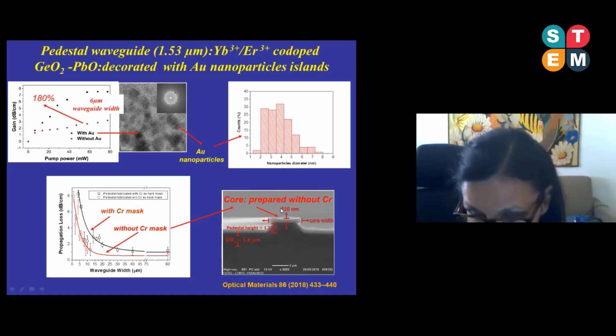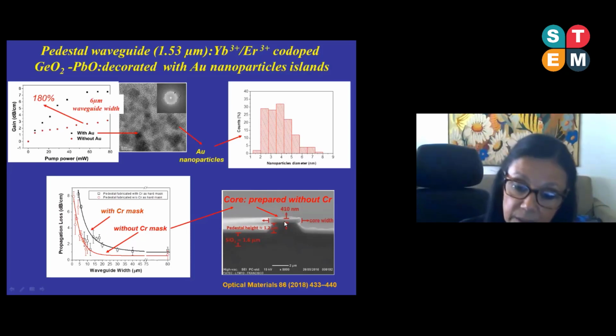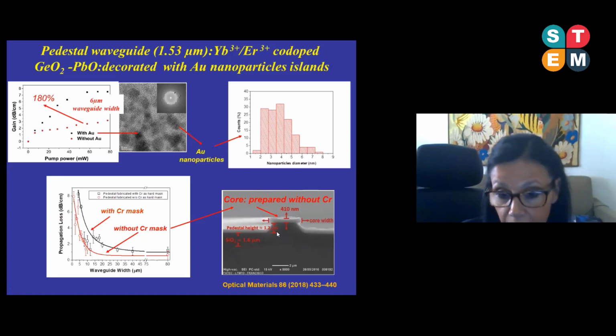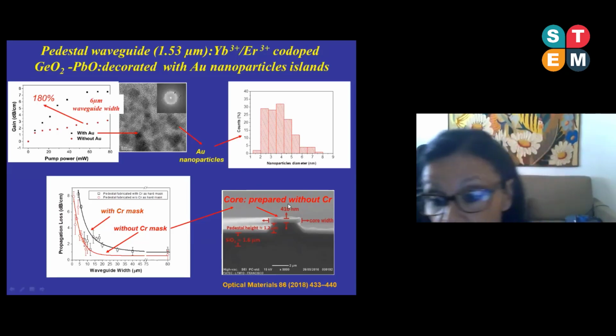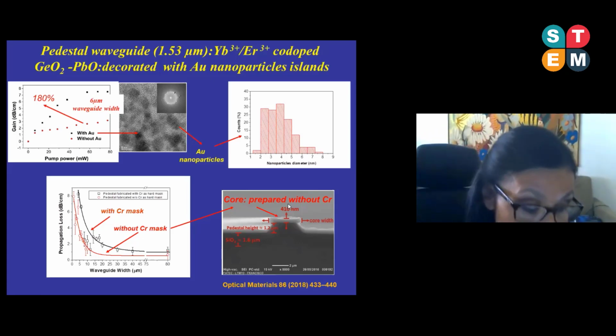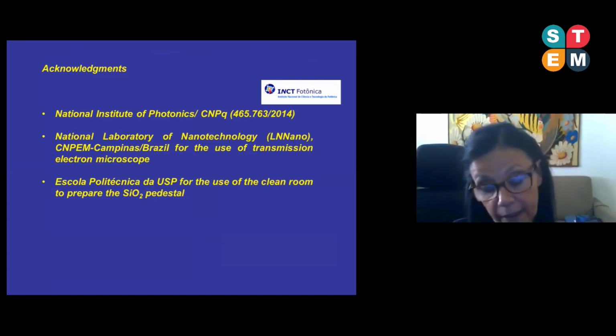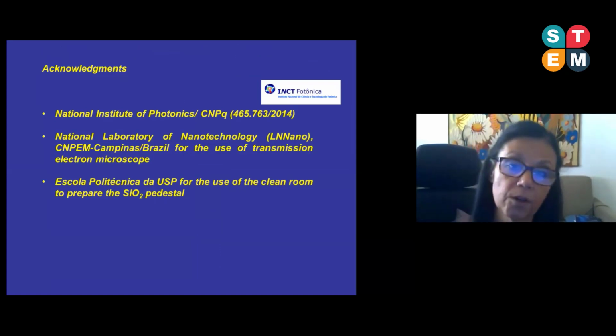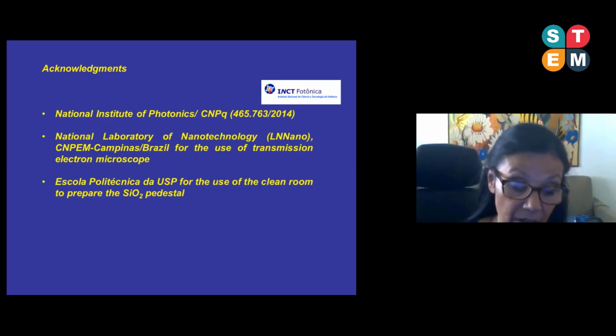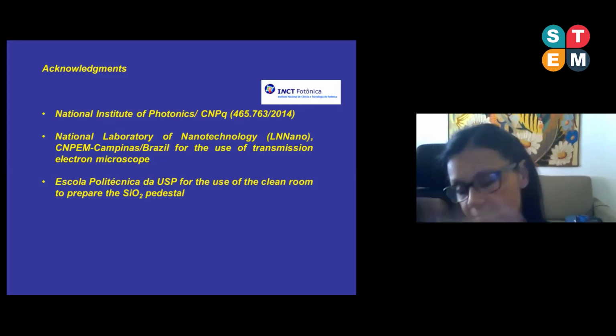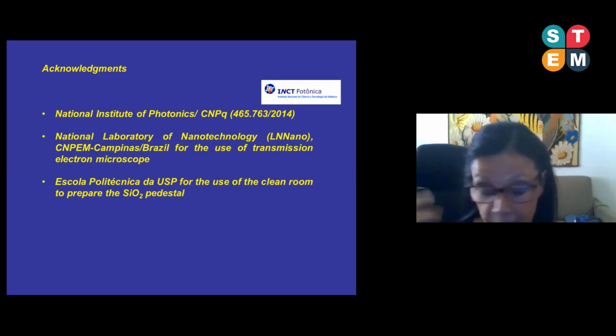In this figure, I show you, also obtained by scanning electron microscope, the profile of the waveguide with a height of about 400 nanometers. And in this case, the silicon dioxide pedestal has a height of 1.2 micrometers. I also would like to add that in this case, the core was prepared without chromium mask. Well, as conclusion for the future, we can think about different configurations for this waveguide. We can produce using nanolithography process, and we can conclude that this material is a potential one for different applications, as I could show to you.